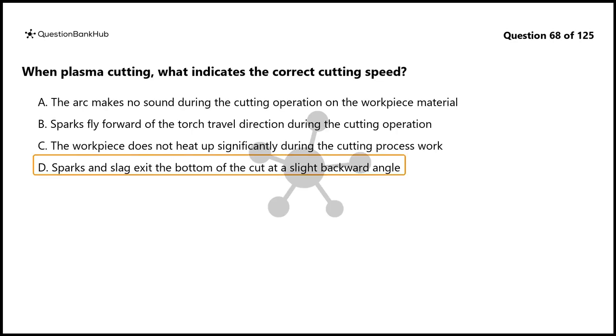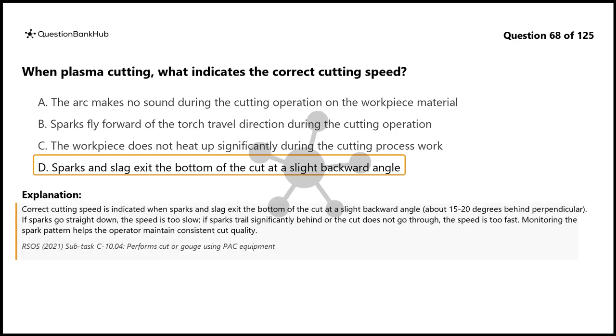The correct answer is D. Sparks and slag exit the bottom of the cut at a slight backward angle. Correct cutting speed is indicated when sparks and slag exit the bottom of the cut at a slight backward angle, about 15 to 20 degrees behind perpendicular.